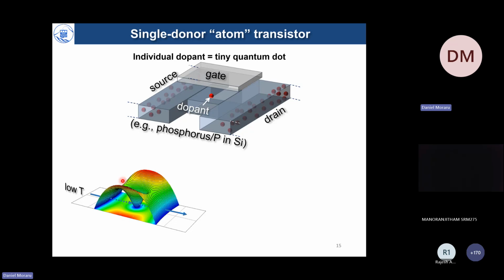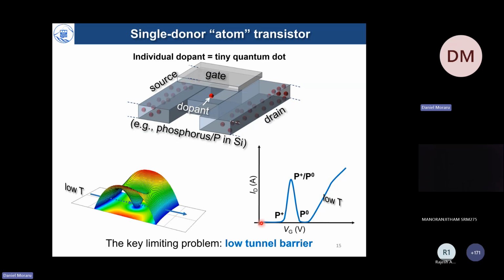That is the mechanism that lets us observe current peaks in the drain current versus gate voltage characteristics, the transfer characteristics, especially at low temperature. These current peaks simply illustrate the different charge states of a phosphorus donor. On the peak, as explained earlier, we can switch the charge state of a phosphorus from P+ to P0. And on the sides, you can keep it either ionized or neutralized. That can be done simply with a gate voltage.